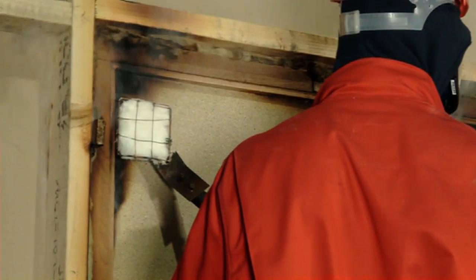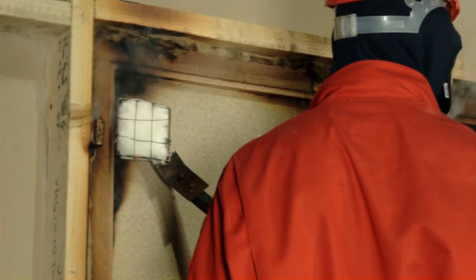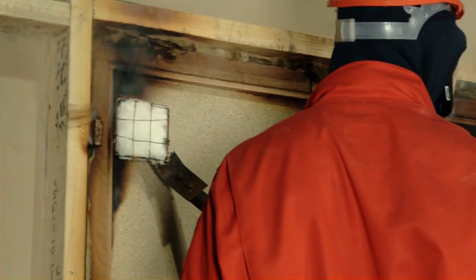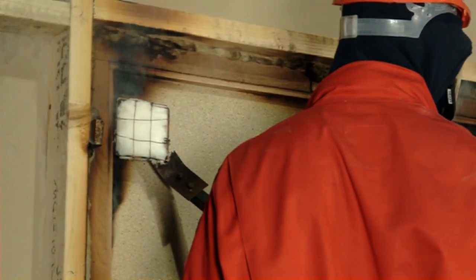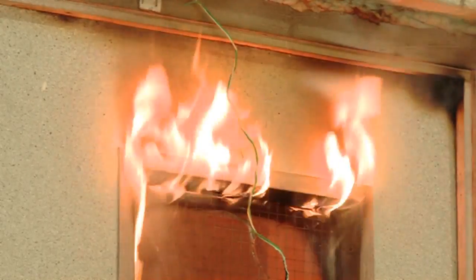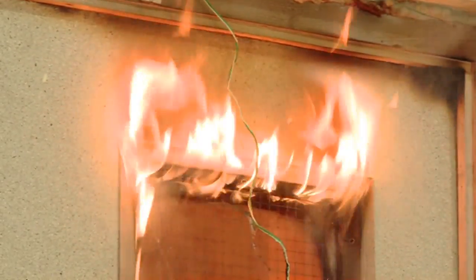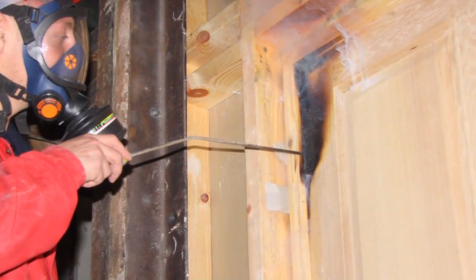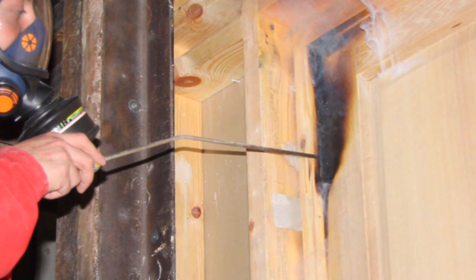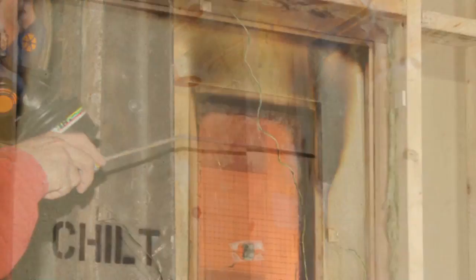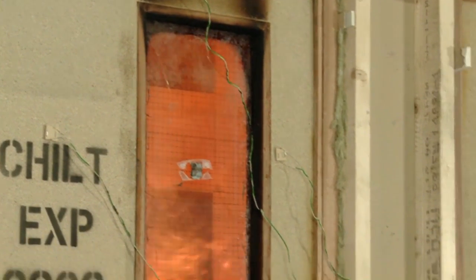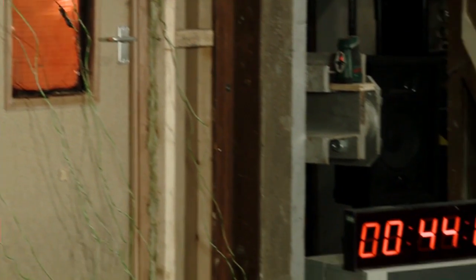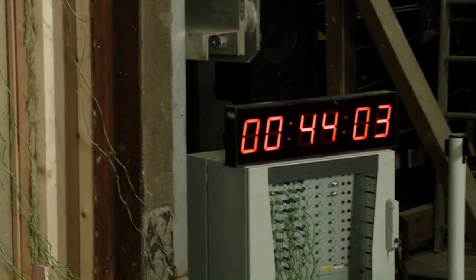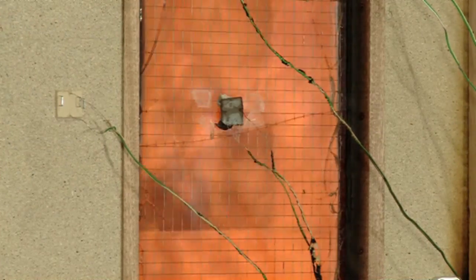A cotton wool pad applied over any gaps or glows on the specimen subsequently ignites. There is continuous flaming for more than 10 seconds. Either of two types of gap gauge can penetrate fissures or gaps in the specimen. As well as recording the time to integrity failure, the time to insulation failure can be found from the thermocouple temperature readings on the unexposed face of the specimen.